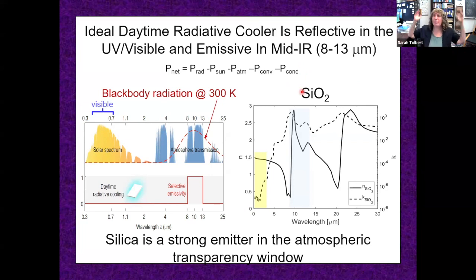So you might say, okay, great, make the whole world out of glass. The problem is silica is such a strong emitter that its refractive index goes way up near its absorption and emission. The ground state absorption and emission are reverse processes. And its refractive index goes up so high that it becomes reflective. And the result is it's not a strong emitter when it's a reflector. So what we need to do to make silica work as our IR emitter is we need to lower its refractive index. And we can do that by making it porous. We basically need to have less silica in any one space.